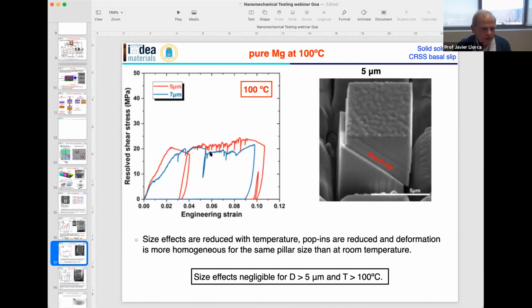If you go to the same thing at high temperature, you can see that the situation is somehow similar, somehow different. When you go to 100 degrees Celsius, again, you have localization of the deformation, you have the formation of some slip bands there, but as you can see, the size effect is much smaller. And actually, if you consider this point here, that is the point where you really start to have non-linear deformation, this will be the point that corresponds to the critical resolved shear stress for basal slip. You can see that at higher temperature, size effects are reduced and the pop-ins are reduced.